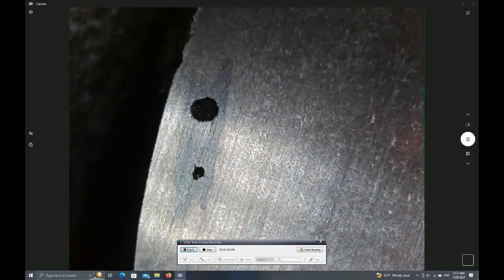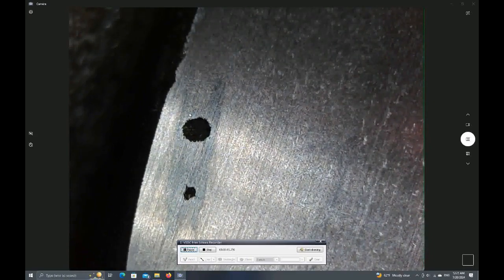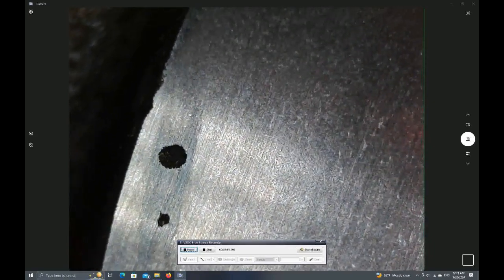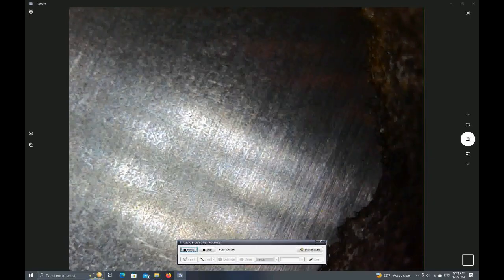So this one had 40 grams of glass, and upon completion, when I took the lid off, as you guys saw in the YouTube short, the glass was perfectly smooth and completely covering the ingot. Therefore, there was no exposed eye in the center like there was on yesterday's crucible. So what I'm seeing here is no sign of humongous carbides, humongous grain boundaries. I'm seeing a remarkably uniform structure here.